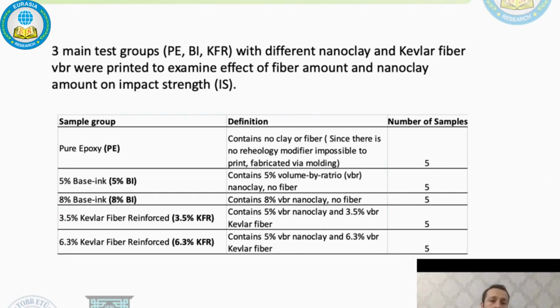The 5% base ink group contains 5% volume by ratio nanoclay but no fiber. In a similar way, the 8% base ink group contains 8% nanoclay but no fiber. The 3.5% Kevlar fiber reinforced group contains 5% volume by ratio nanoclay and 3.5% volume by ratio Kevlar fiber.